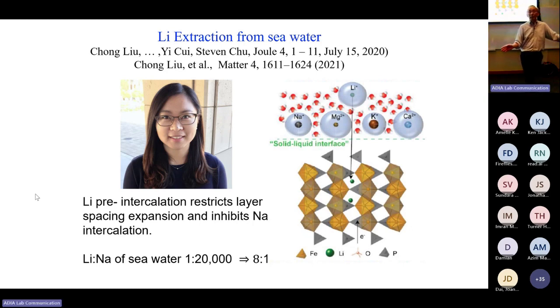Right now, we get lithium mostly from underground aquifers, very salty water. You pump it up, you let it evaporate a couple of years. It gets this really icky stuff. In the process of pumping it up, you've taken underground water with all its contaminants and you've polluted the ground. In addition to that, because you're pumping so much salt water out of the saltwater aquifer, freshwater aquifers, which are near the surface, then sink down and become salty water. So you're depleting the fresh water as well. So this is not a good way to extract lithium.